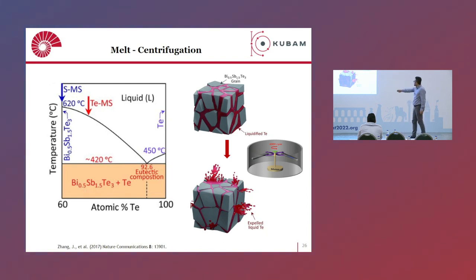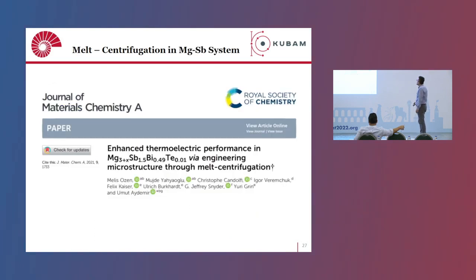Okay, the idea was this: as I said, you have bismuth antimony telluride. If you add tellurium, you have this eutectic point here. If you just heat this material around 500 degrees, you can remove this melt, and you can create such microstructural features. So we thought, okay, why not apply this to magnesium antimonide?